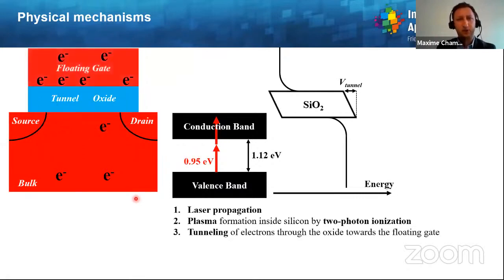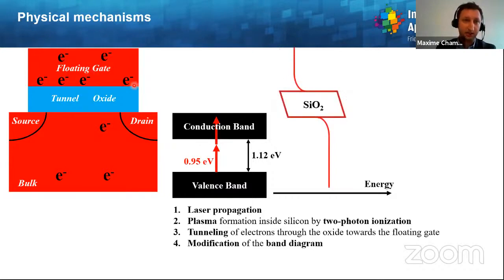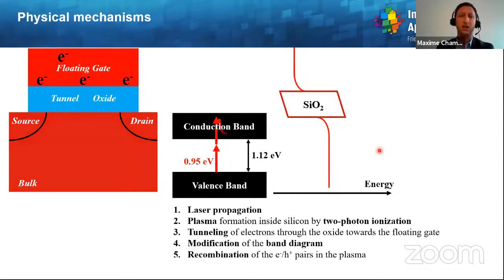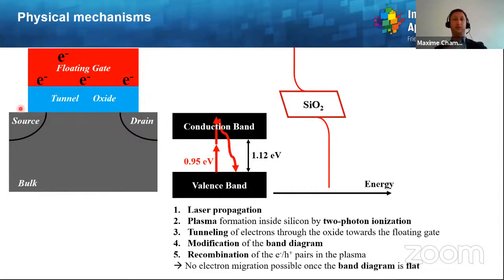Then some electrons will be able to tunnel through the oxide layer toward the floating gate. Then this increase in the negative charge will lead to a change in the band diagram. And finally, the electron and hole pairs that have been produced in the silicon substrate will recombine, and in the end you have more electrons in the floating gate than initially. And by repeating this from one pulse to another, you can clearly see that no electron migration will be possible once the band diagram is completely flat.